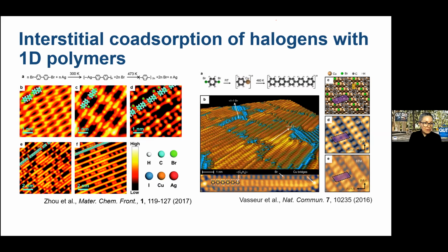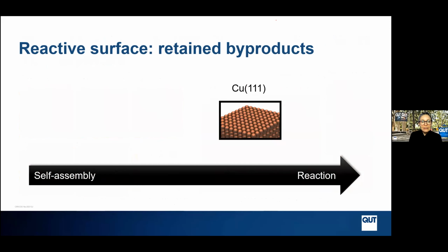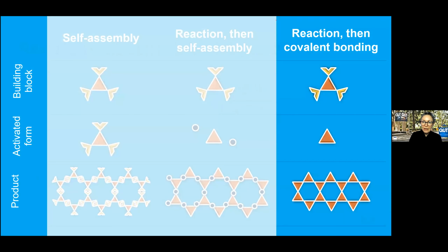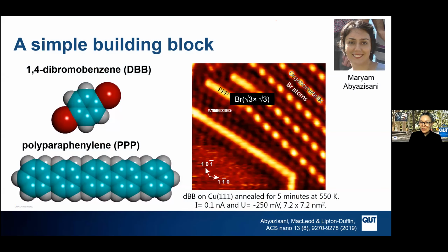And here you see a couple of works on Ullmann dehalogenation that show just how prevalent it is. Retained halogens are really commonly observed as interstitials between the polymers or the organometallics that are produced through this process. So here's our reactive surface where we're looking to retain the byproduct and then see if we can remove it with a post-treatment. So reaction, then covalent bonding process. And this is the molecule that we were working with. It's very simple, 1,4-dibromobenzene, which will polymerize after covalent bonding into polyparaphenylene.